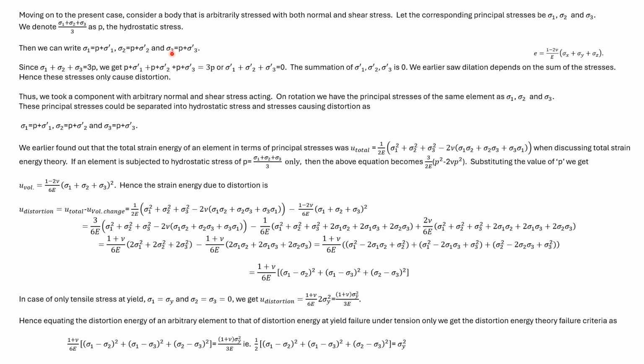Now substituting these values, we get 3P plus sigma dash 1 plus sigma dash 2 plus sigma dash 3 is equal to 3P, which means sigma dash 1 plus sigma dash 2 plus sigma dash 3 is equal to 0. Now we earlier saw that dilation depends upon the sum of the stresses. So if the sum of the stresses is 0, then there's no dilation, and this means that there's no volume change. Hence these three stresses only cause distortion. Hence in sigma 1, sigma 2 and sigma 3, P causes volume change and these three stresses cause distortion.